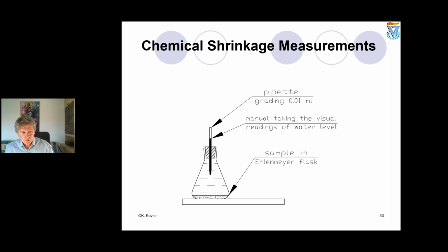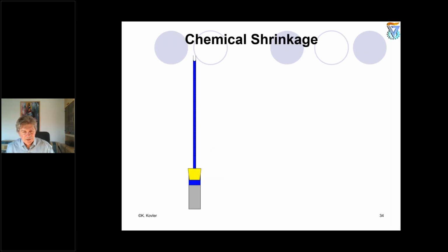Then I would like to explain briefly how Le Chatelier measured this chemical shrinkage in his experiments and how we can measure it now. This is a very simple test he did. He took a flask, cast a very thin layer of cement paste in the bottom, filled it with water, and followed the drop of the meniscus in this very thin tube. From following the meniscus drop, he understood that some water is disappearing.